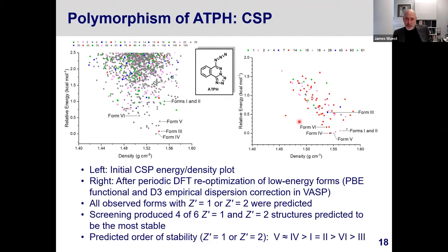And the good news is that here's the result of that reordering. It still indicates a high density of potential forms. All of the forms that we have observed experimentally match structures that are predicted to exist. Now, that's good news. And the other good news is that of the 6 structures predicted to be the most stable, we have already found 4 of them.